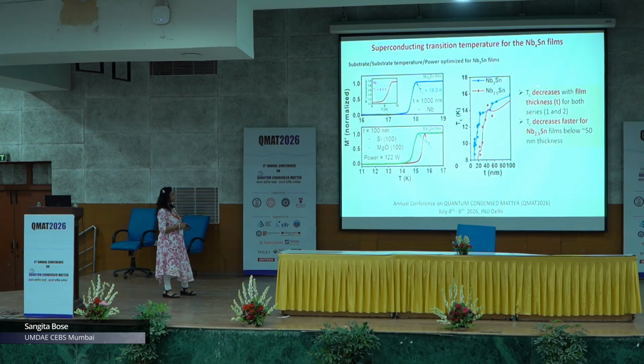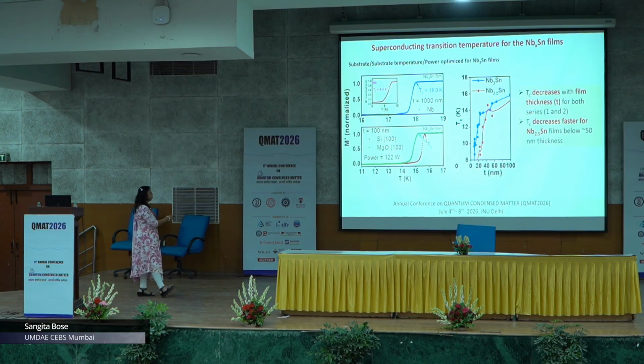When we decrease the thickness, we see a decrease in the superconducting transition temperature, and for both the series we see almost a similar trend. However, the Tc decreases faster for niobium 3 tin films below 50 nanometer thickness.